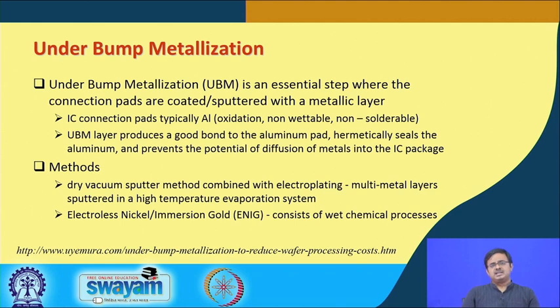Okay. Sometimes the connection pads are also made of copper, but there also you need under bump metallization, because even though it does not have all the drawbacks of aluminum, it is also not a very amenable coating. But aluminum being most common, I have mentioned some of its drawbacks. So, what does UBM do? The UBM layer produces a good bond to the aluminum pad. Okay. So, as I said before, under bump metallization is a metal layer that covers these aluminum pads. This metal bonds well with the aluminum pad, it seals the aluminum hermetically.